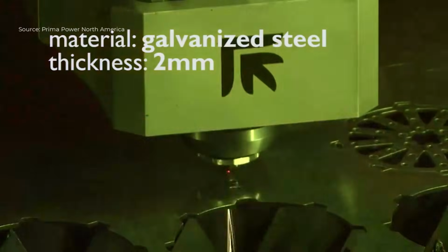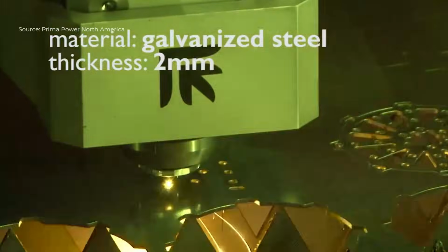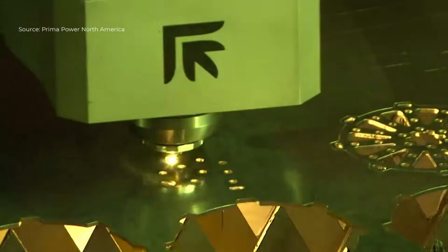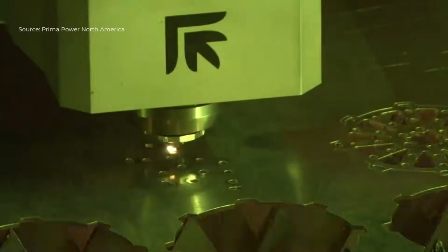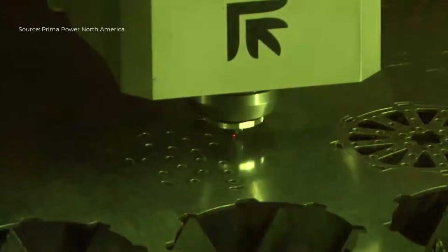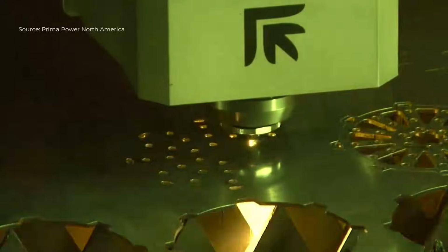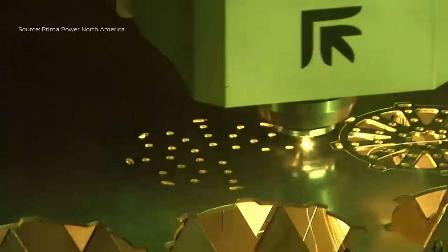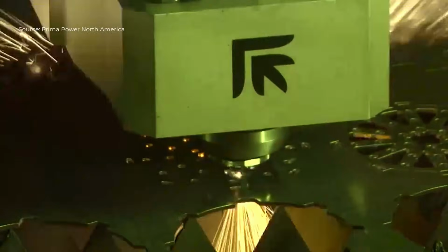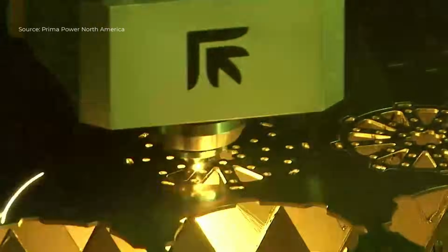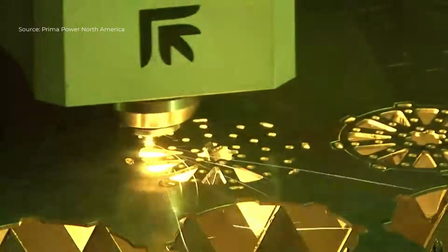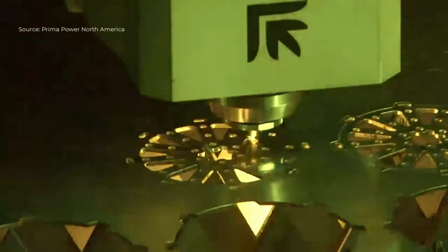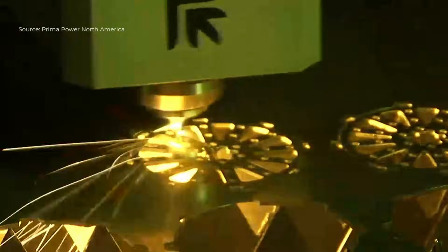The cutting process starts with thin, galvanized steel sheets with a thickness of 2 millimeters. After the sheet is clamped and aligned, the fiber laser head moves rapidly to the programmed starting position. The 4 kilowatts fiber laser is activated, producing a highly concentrated laser beam that pierces the material almost instantly. Thanks to the optimized piercing technology, the laser creates a clean entry point with minimal spatter. The cutting head then follows the programmed cutting path at high speed, producing smooth edges and precise contours. The efficiency of the fiber laser is clearly visible as thin material is processed quickly while maintaining excellent dimensional accuracy.